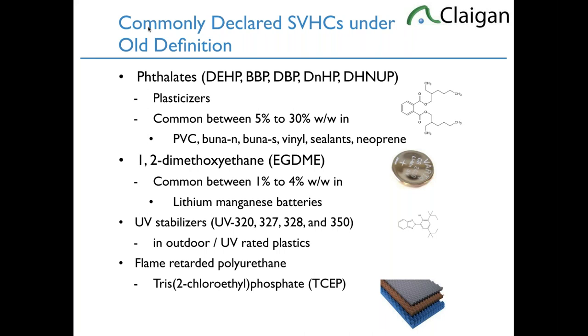These are the phthalates that make PVC bend. PVC is normally rigid, like your water piping, and the way you make it bend is you get a plasticizer, historically the phthalates, and they get between the vinyl chloride strands and push them farther apart. Technically, it's called swelling. By pushing them farther apart, they become more fluid and flexible and bend.